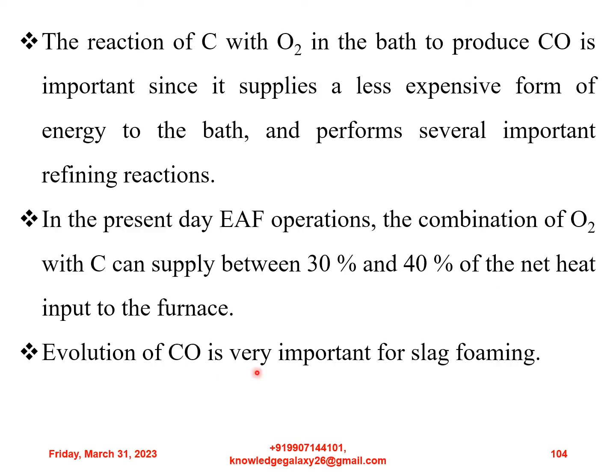Evolution of CO is very important for slag foaming. Coupled with a basic slag, CO bubbles are trapped in the slag, causing it to foam and helping to bury the arc. This gives greatly improved thermal efficiency and allows the furnace to operate at high arc voltages even after a flat bath has been achieved.